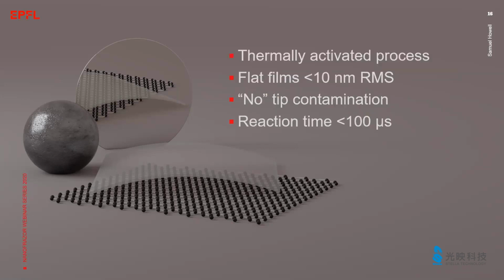As a basic requirement for a material to be useful for thermal scanning probe lithography, there must exist a thermally activated process in a temperature range which can be reached by TSPL. We have seen that the temperature necessary to induce a reaction can be considerably higher for TSPL than at the macroscopic scale. So to create high resolution patterns, it is also necessary that the material can form flat films and does not contaminate the tip. And if patterning speed is a criterion, the reaction should be completed within less than 100 microseconds under the tip.